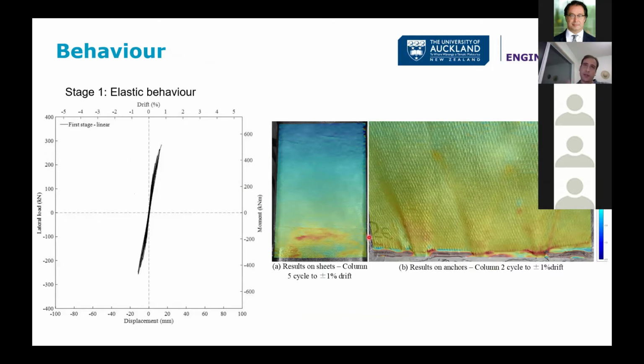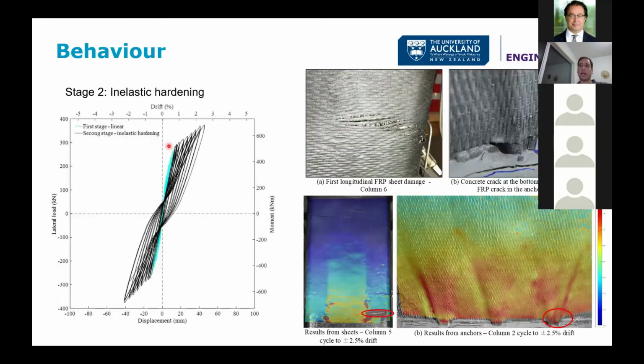I observed 3 behaviors or 3 stages. The first one, linear elastic, up to the point when the FRP first debonded from the column in the back. Then an inelastic hardening. This is column 6, by the way, so you can see it's quite symmetric. In this stage, all the FRP debonded from the bottom all the way to the top until the first FRP rupture. So that's the peak point where the FRP ruptured for the first time, whether it was an anchor or a sheet.